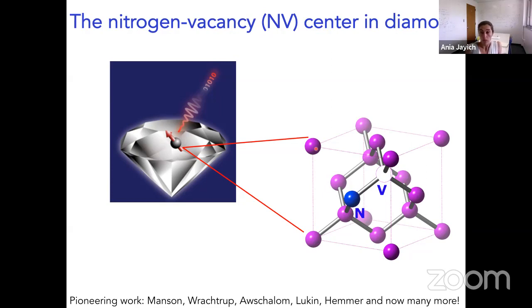Then the carbon atoms of the lattice are mostly nuclear spin free. 99% of carbon atoms are carbon-12, which has no nuclear spin. And with more isotopic purification, which is possible, one can get even lower background nuclear spin impurities. Diamond can also be grown or formed with very few other defects, other paramagnetic impurities that could lead to decoherence, easily to the tune of a few parts per billion.